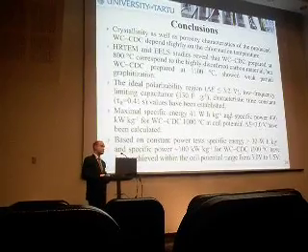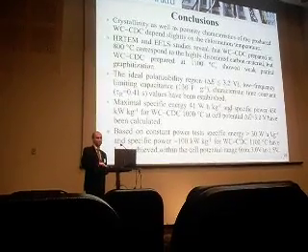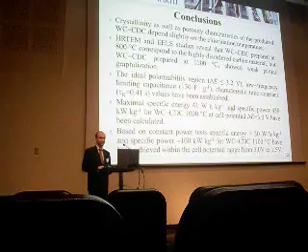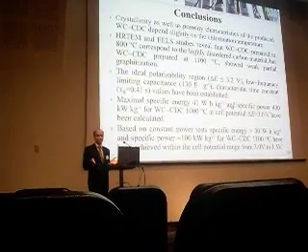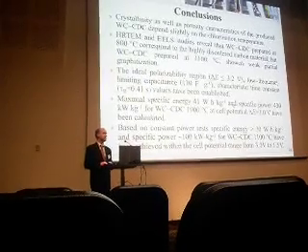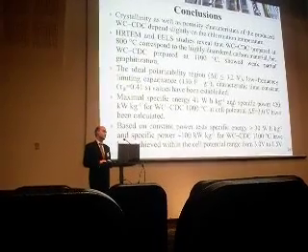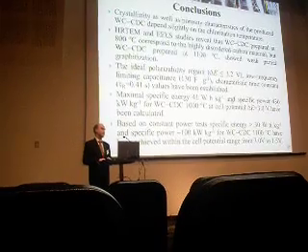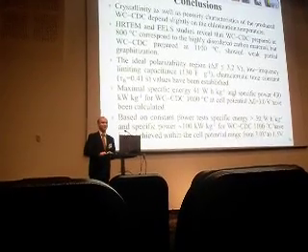The ideal polarizability region is up to 3.2 volts, and the maximum specific energy is about average. However, the specific power is about twice what had been achieved previously. And based on these measurements, I can say that we have a very promising material.